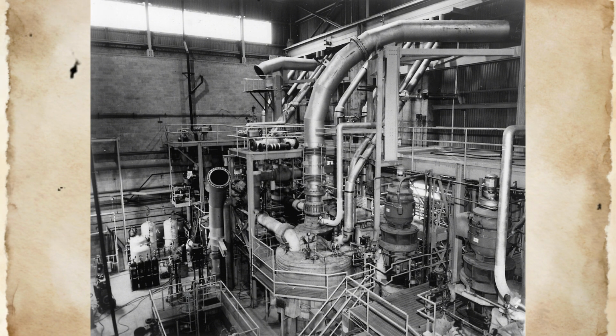The thermal analysis performed during post-incident investigation confirmed that the observed progression from initial flow blockage to fuel damage was consistent with calculated thermal hydraulic conditions under partial flow restriction scenarios. The metallic uranium fuel properties, sodium coolant characteristics, and zircaloy cladding behavior all performed according to established materials data when subjected to the thermal conditions created by debris blockage.